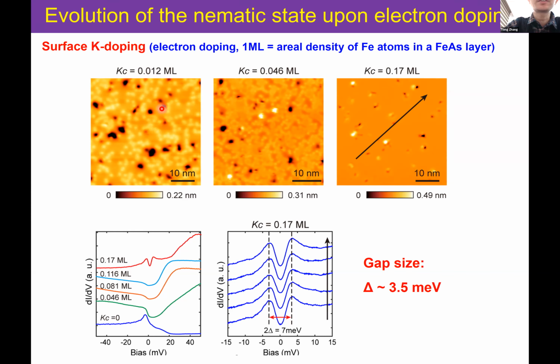Actually, it's on another STM system. We dope the surface with different amounts of potassium atoms. So I can show the topography at a certain coverage, 0.17 monolayer. Here, 1 monolayer is the density of the iron atoms in the iron arsenic layers. At this coverage, the surface is flat. Actually, it formed an ordered structure. And as the potassium coverage increases, you can see the spectra evolve. At this coverage, a larger gap showed up, and this gap has a size of 7 millivolts.